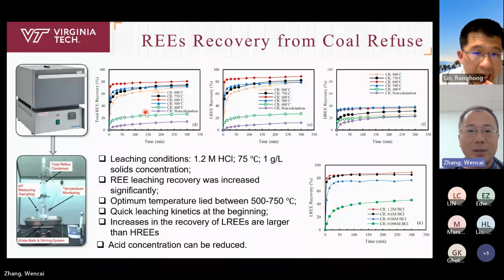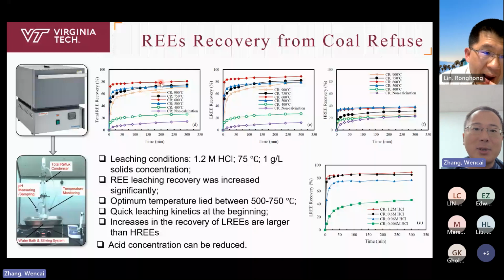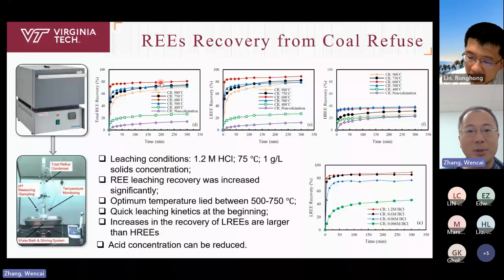So these are the results we obtained in 2018. For example, this is the total rare earth leaching recovery, and the original leaching data is here. This line is the leaching recovery of rare earths from the raw coal refuse, and the line above is the leaching recovery of rare earths from coal refuse roasted at high temperatures. For example, the highest we got was roasted at 600 degrees C. This is interesting. We didn't add any chemicals during the roasting, but we found that the rare earth leaching recovery increased a lot, from around 10% to over 80%. This is encouraging, but it also confused us because we don't know why, since we didn't add any additives into the system.